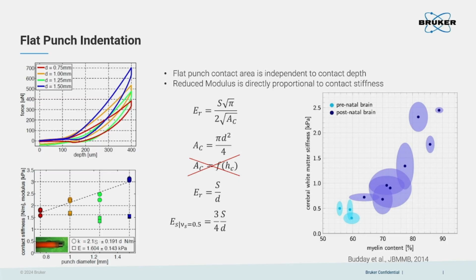This is actually a brain cell, and we test them at different ages. This is the very brand new prenatal brain, so the myelin is not so much, and the modulus or the stiffness will be lower, maybe the lowest. When the brain cell starts to develop and grow up, the myelin content goes up, and correlatively, the modulus of this brain cell also goes up. So we get a very direct, straightforward idea that this modulus is highly related to the myelin content for a brain cell test.